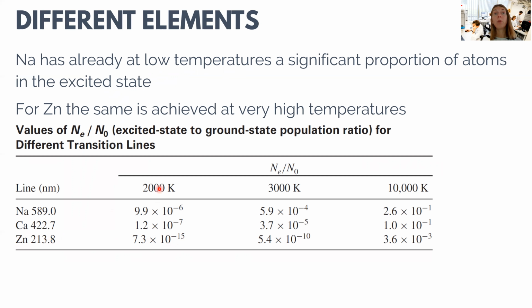And of course, we see that when we increase from 2000 Kelvin to 3000 Kelvin, then for all elements here, this ratio is increasing. So we have an increasing amount of this excited state present in the flame where we do the measurements. However, this effect is still not sufficient for zinc, for which still only 1 in every 10 to the power of 10 atoms is actually in the excited state. And only when we manage to increase the temperature to 10,000 Kelvin, we get a sufficiently high ratio of excited to ground state for the zinc atoms. And of course, also for calcium and sodium, it is increased.